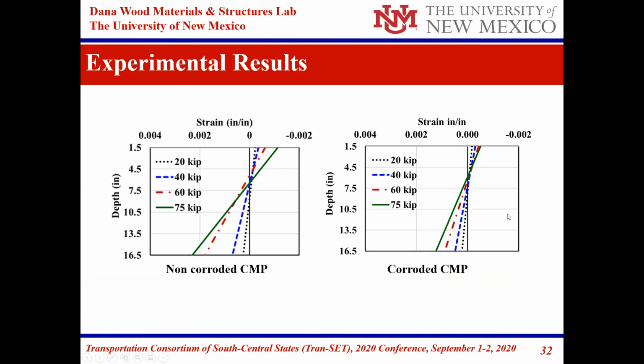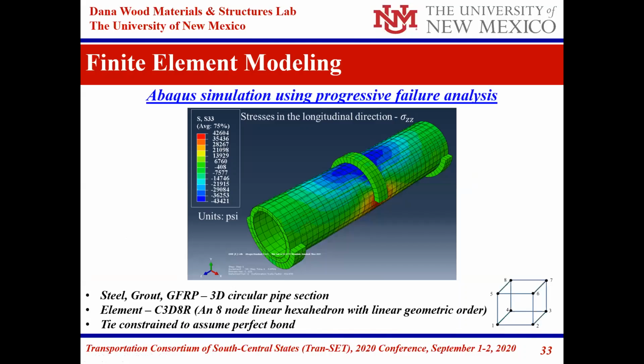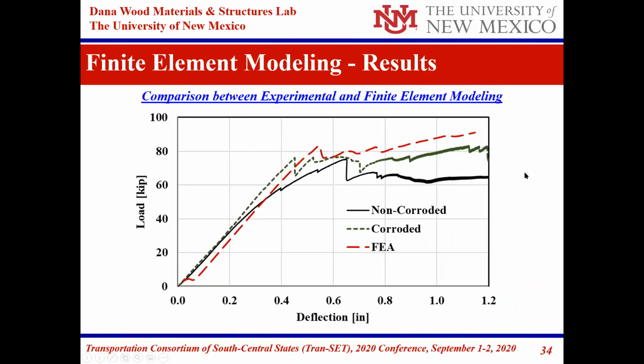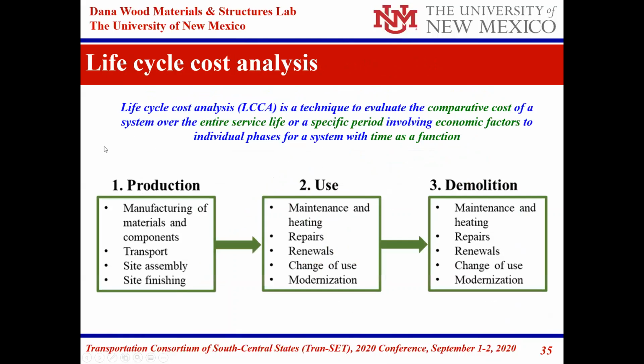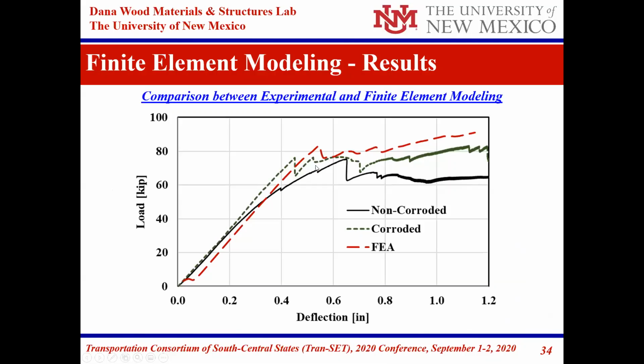We did finite element modeling of the system to simulate the failure and to understand the progressive failure that is happening in the tension and the compression. And the finite element model in comparison to the experimental work is here. What the finite element model showed us basically is that the main issue is the joint, and the fact that the joint would always lead to the final failure of the load because of the way that this joint in the GFRP, in the corrugated pipes, is developed. But again, as I've shown, the load capacity is in the 70 kip range, which is very high load compared to this pipe.